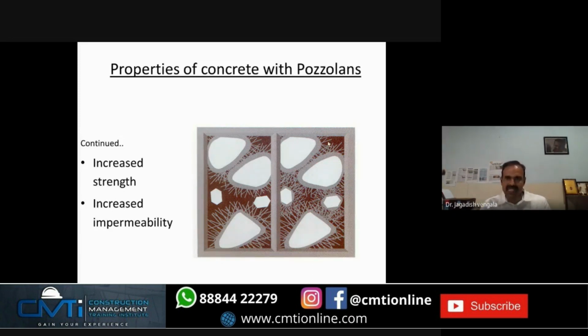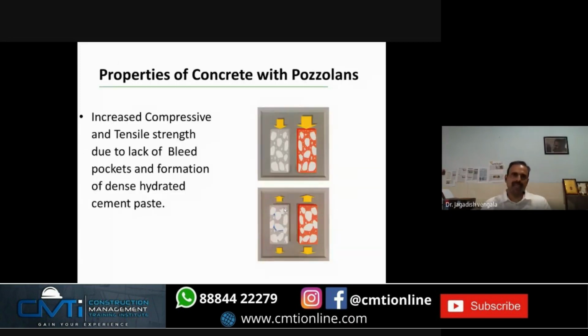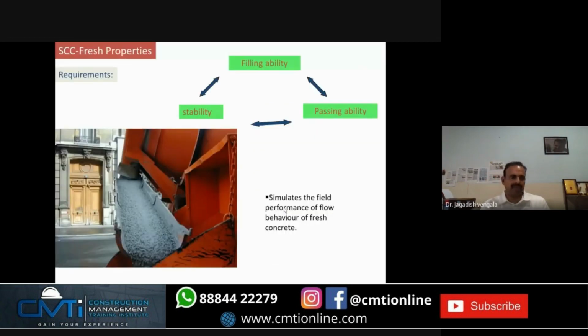What I mean to say is, in the first case and second case, you can see the pictures. The yellow color is the voids, if you say. The second picture, which contains pozzolan, has fewer voids, as you see in the gray color. Also, by adding pozzolanas, the bleed pockets get reduced and you get a dense hydrated paste, which by testing gives increased compressive and tensile strength.